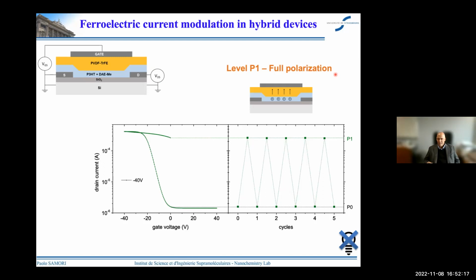We place the top gate, this ferroelectric gate, and we wanted to modulate the current through the junction only by sweeping, first of all, the gate voltage. We do this in the dark to demonstrate that we can switch the current through the junction thanks to the ferroelectric input. First, we apply plus 40 volts to erase all the previous polarization states, and we go down here. Then we apply minus 40 volts, and that allows us to reach the highest current possible, where we have the highest accumulation of charges at the interface with the organic semiconductor. This state is called P1. You can see that all the dipoles are aligned up.